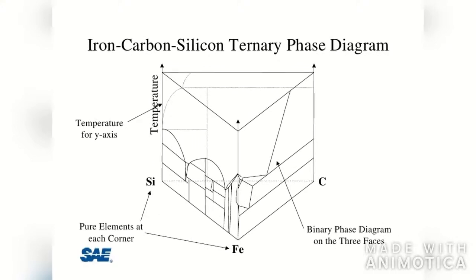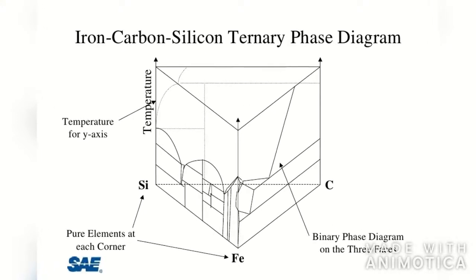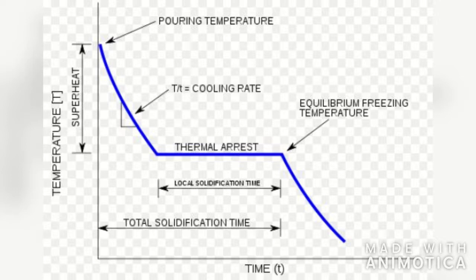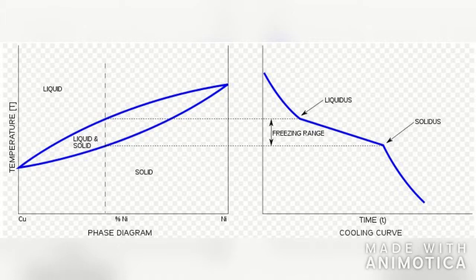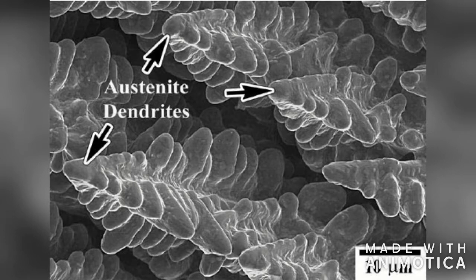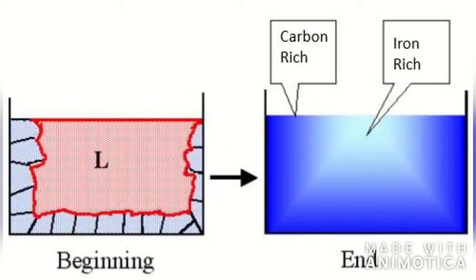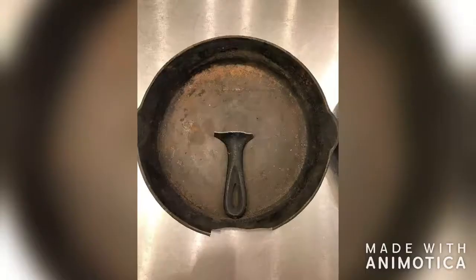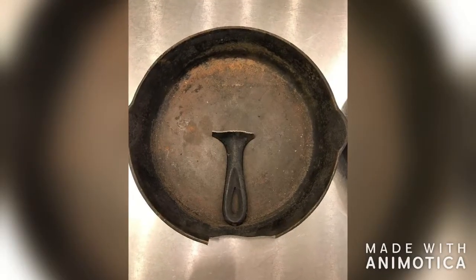Lastly, the composition of the metal has a large impact on how solidification occurs. Pure metals have a single solidification temperature, simplifying this step in the process. Alloyed metals, however, can be more complicated. Except for eutectic alloys, solidification for most alloys occurs over a range of temperatures rather than at a single point. This results in one of the phases solidifying before the others. From this, we tend to see 1. Dendritic growth, where solid portions of dendrite structures from one phase trap small islands of liquid metal of another phase, and 2. An imbalance in composition between the metal that is solidified and the remaining molten metal. These solidification effects can be detrimental to the quality of the cast iron skillets and should be avoided if possible.